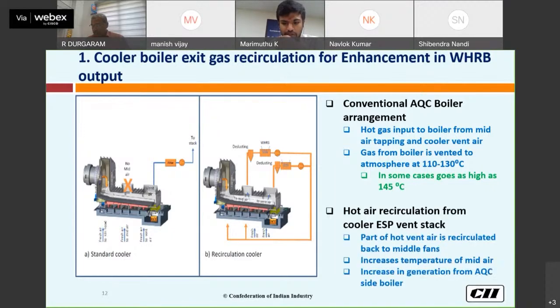In the recirculation cooler, part of the hot air from the stack, meaning after the ESP, is recirculated to the middle fan of the cooler, where our tapping is taken for the WHRB. So if instead of giving ambient air we give hot air, what will happen? It will increase the heat input to the WHRB. This will help in power generation, meaning it will help in increasing the generation.